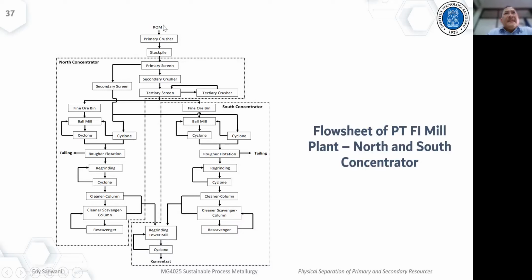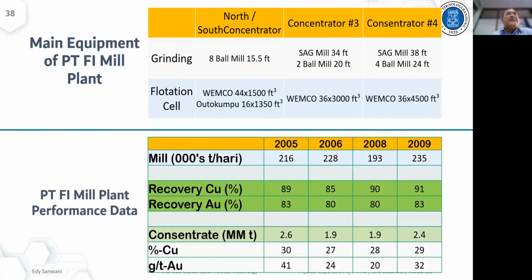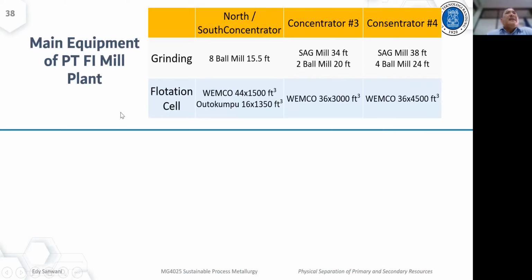The copper grade in the ore is usually less than 1%, usually around 0.8, 0.9, even 0.7% copper, and the concentrate will be produced at a grade of more than 20% copper, which is the grade limit fit for the smelting process. Okay. Just for example, this is the main equipment of the PT Freeport Indonesia mill plant, the grinding and the flotation cell.